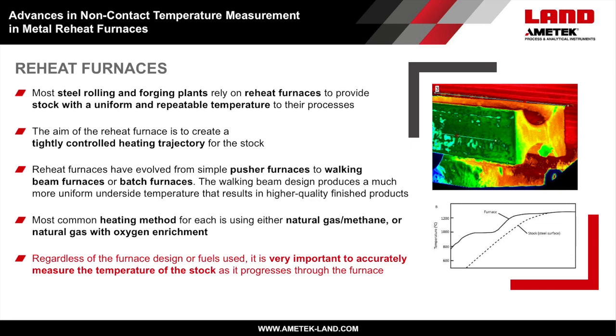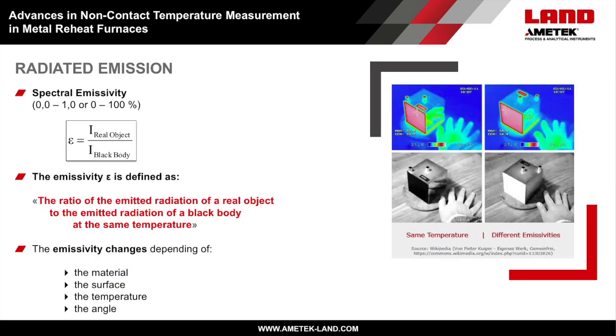Mainly used heating methods are natural or methane gas and natural gas with oxygen enrichment, which is more efficient. Regardless of the furnace design or fuels used, it is very important to accurately measure the temperature of the stock and its progress through the furnace. The main challenge of measuring accurate stock temperatures in reheat furnaces is the interaction of the direct emission of the object, whose temperature should be measured, and the mostly hotter background temperatures of the reheat furnaces.